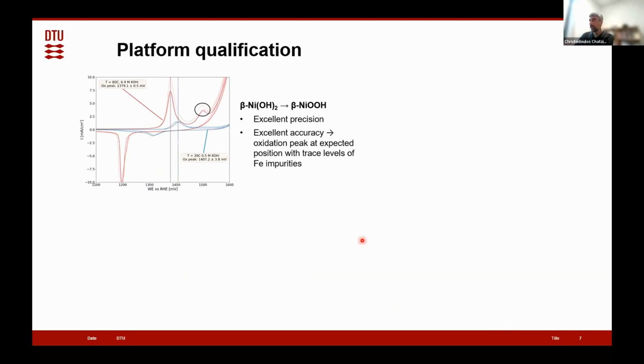We have performed very diligent qualification of the platform. Here you see, as an example, the nickel hydroxide to nickel oxyhydroxide transition, both at 30 degrees Celsius, half a molar KOH, where academic literature exists and we can compare with, but also at 80 degrees Celsius and 6.9 molar KOH. Indeed, here you see 4 repetitions at each condition. You see there is excellent reproducibility, excellent precision, with very little standard deviation of the peak position in each case, but also excellent accuracy with the peak position actually being where it would be expected in an electrolyte with trace levels of iron impurity. And the transition towards lower potentials with increasing temperature and increasing intensity of the peak.